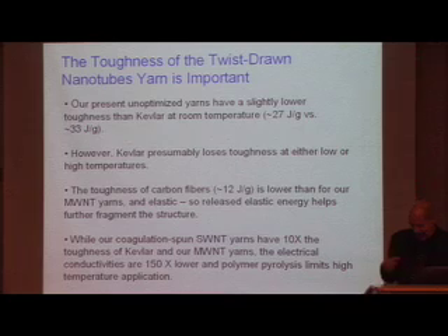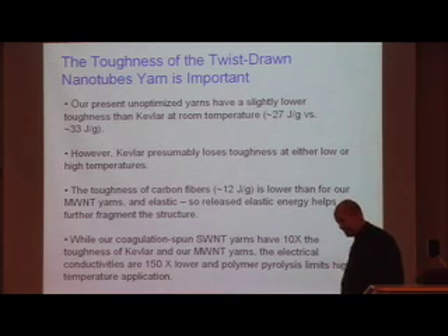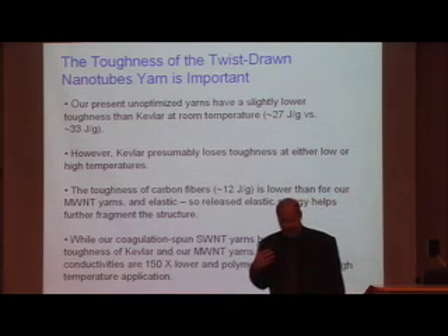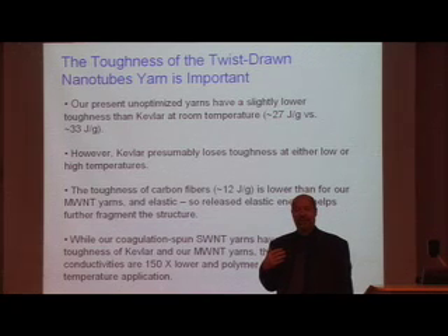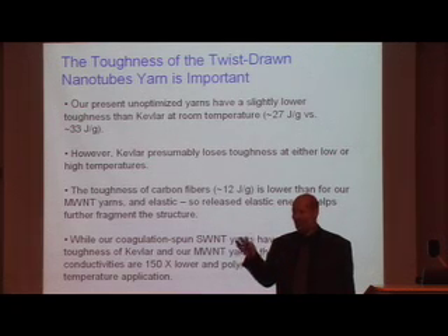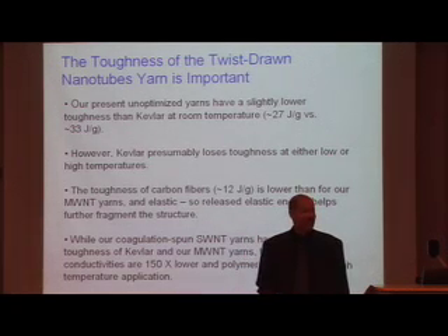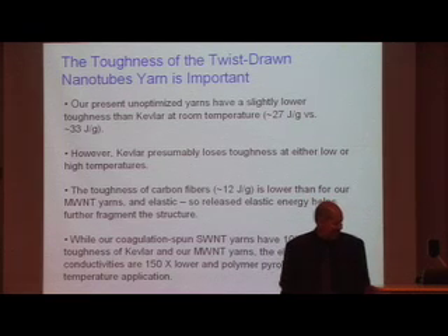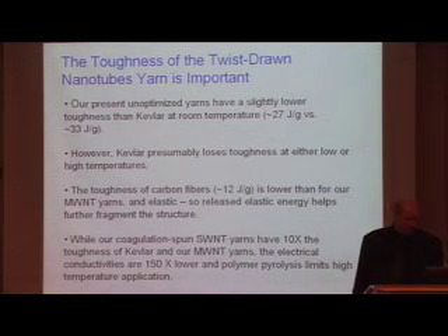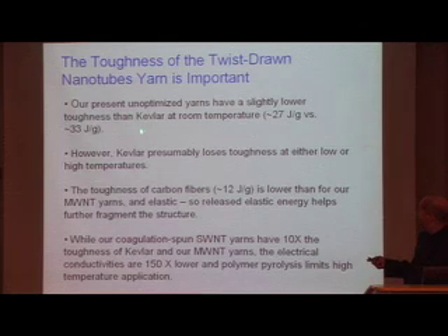However, if you knot Kevlar, it loses its toughness. If you expose Kevlar to ultraviolet light, it loses toughness. If you take it to too high a temperature, too low a temperature, it loses toughness. So the mechanical properties of our yarns are very interesting and still far from where we will eventually be able to take them.